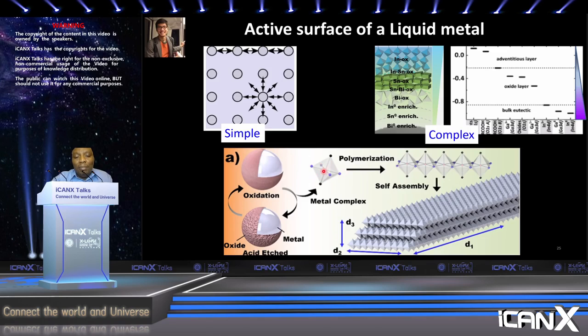chelated organometallic adducts of the same metal ion, which then, if I choose my chelates well, I can actually polymerize and self-assemble to create a material that looks like this. In this case, direction D1 will be controlled by the polymerization. Directions D2 and D3 will be controlled by the self-assembly process.